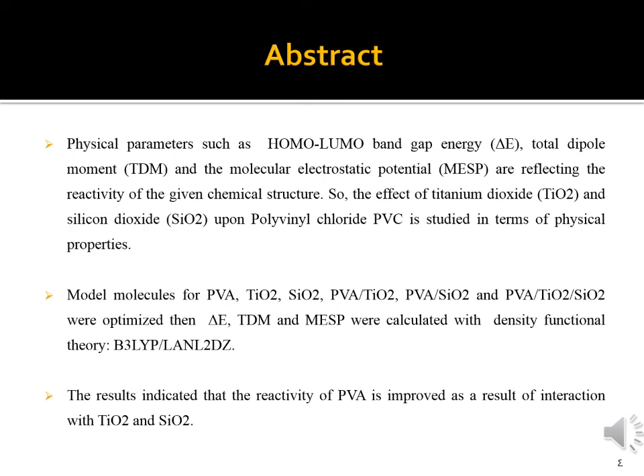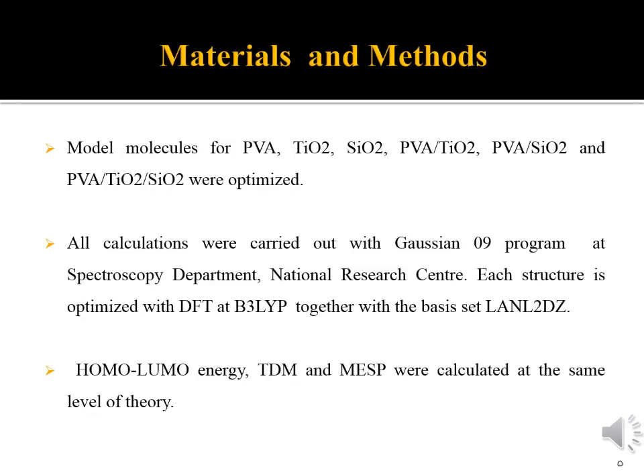So, the effect of titanium dioxide and silicon dioxide upon polyvinyl alcohol is studied in terms of physical properties. Model molecules for polyvinyl alcohol, titanium dioxide, silicon dioxide, polyvinyl alcohol titanium dioxide, polyvinyl alcohol silicon dioxide, and polyvinyl alcohol titanium dioxide silicon dioxide were optimized. Then, delta E, TDM, and MESP were calculated with density functional theory B3LYP with basis set LANL2DZ. The results indicated that the reactivity of polyvinyl alcohol is improved as a result of interaction with titanium dioxide and silicon dioxide.